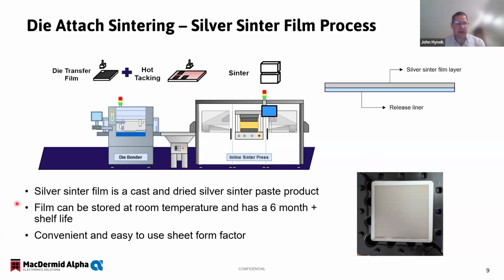Another benefit is that it can be stored at room temperature and has a 6-month or greater shelf life. We're currently doing studies to show that it can last longer than 6 months, but right now we know that the film does not change characteristically over 6 months in typical storage. Room temperature, but it has to be in a nitrogen environment, although in the typical locations where this process would be done, nitrogen is pretty readily available. And it's in an easy and convenient to use sheet form factor.